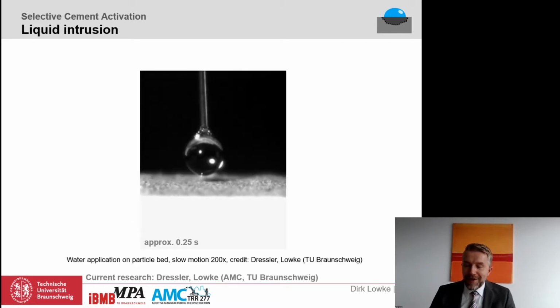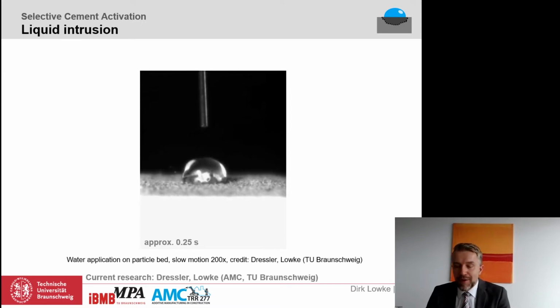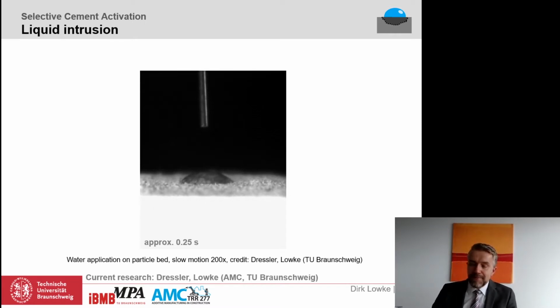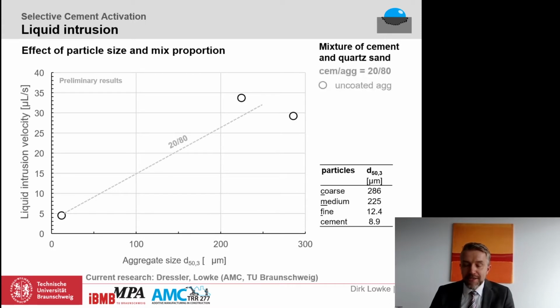Ladies and gentlemen, now we will have a closer look at the water intrusion into the particle bed. Here you can see how a water droplet hits the particle bed and intrudes into it. In real time, this process takes about 0.25 seconds. In these investigations, we are interested in the intrusion velocity and how we can control the intrusion behavior into the particle bed. In the first step, we focused on the effect of particle size and mixture proportion. Therefore, we investigated mixtures of cement and three types of aggregates, namely a fine, a medium, and a coarse quartz sand. And as you can see here, the intrusion velocity increases with particle size.